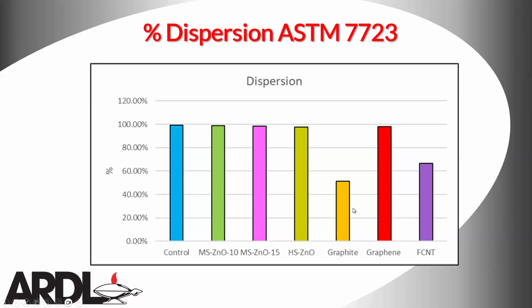And after looking at the data and thinking about it, it actually made sense to us, because graphite is a lubricant. When you're adding it in a rubber compound, you're going to basically reduce the viscosity of the bulk of the material in the mixer, which is going to reduce your shear properties. Plus, because it is a lubricant, you're going to have a lot of slippage within the mixer as well. And so I don't think what you're seeing here is particularly poor dispersion of graphite, because there's a small amount of it in there. What I think happened is because the graphite is acting as a lubricant, what you're seeing is poor dispersion of the carbon black and poor dispersion of the filler.